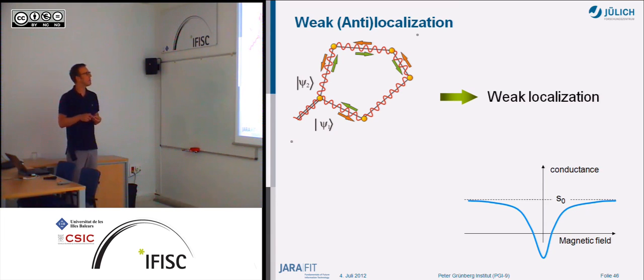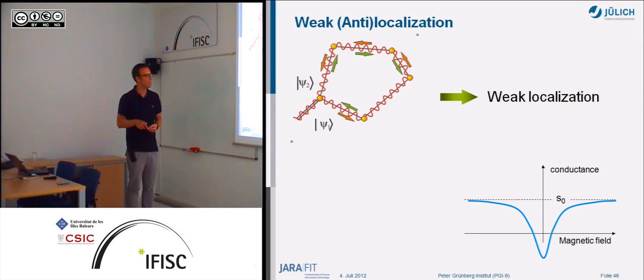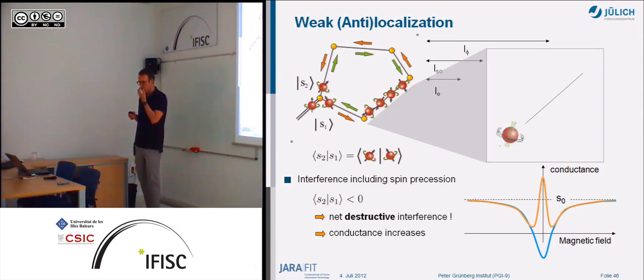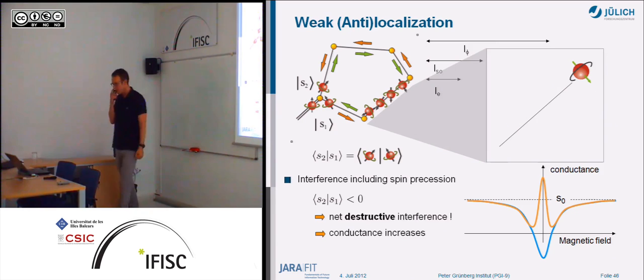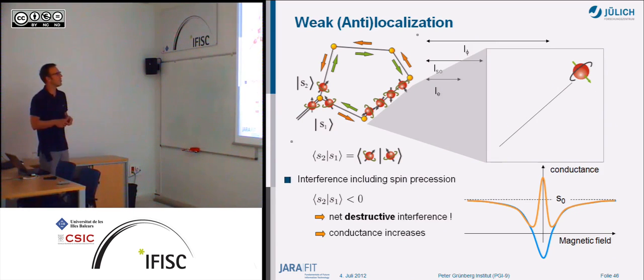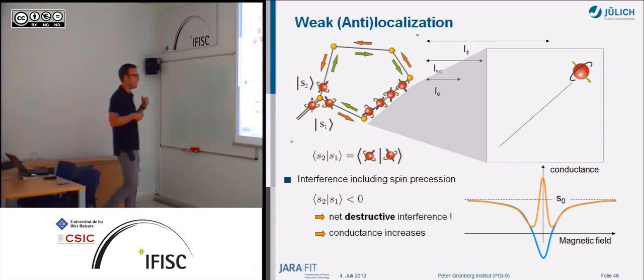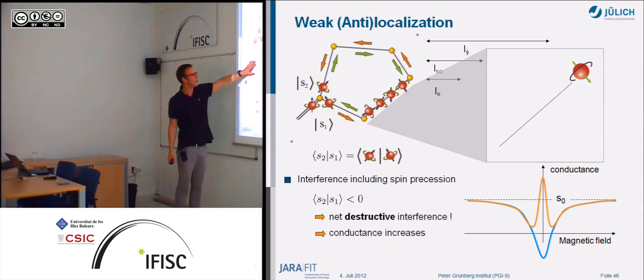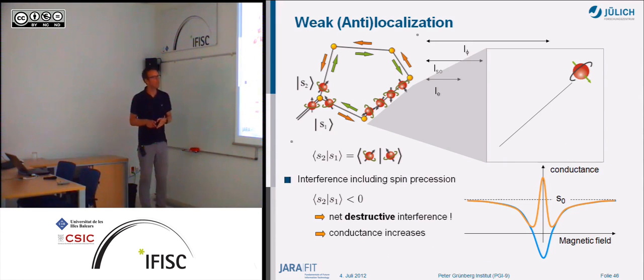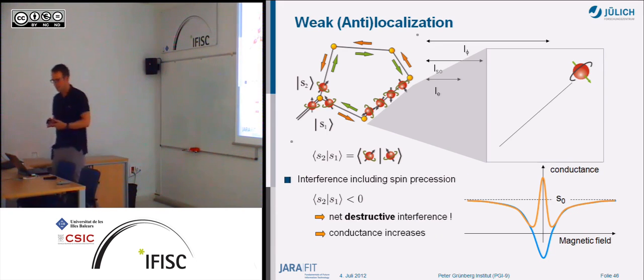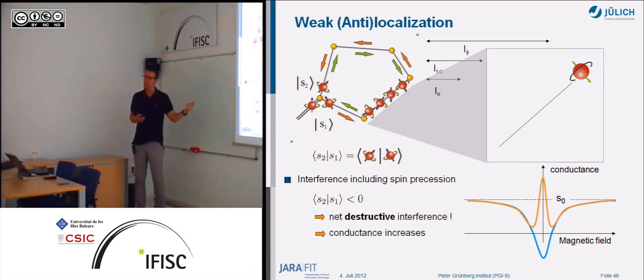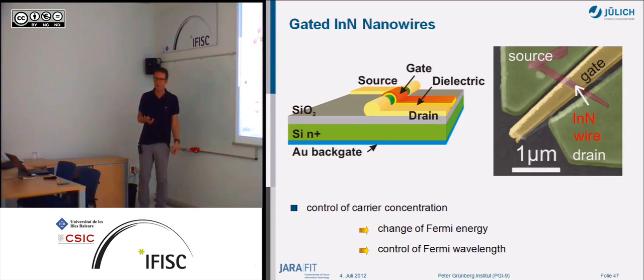By applying a magnetic field, you change the phase and destroy the constructive interference, and that's why the conductance goes up. So that's the usual weak localization experiment you can do. But if you now include spin and have some spin precession along this path, then the dip in the conductance switches to a peak, and you have a net destructive interference. You have to include the spin interference for that mechanism, and then you have a conductance increase. And this conductance increase can be used to get information about the strength of spin-orbit coupling. That's a very convenient way to get information, first of all, about the existence of spin-orbit coupling, but you can also try to get some numbers for it.